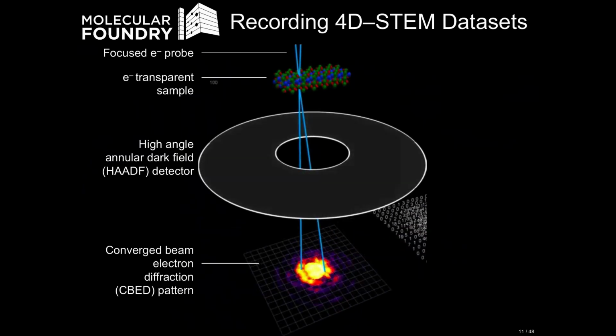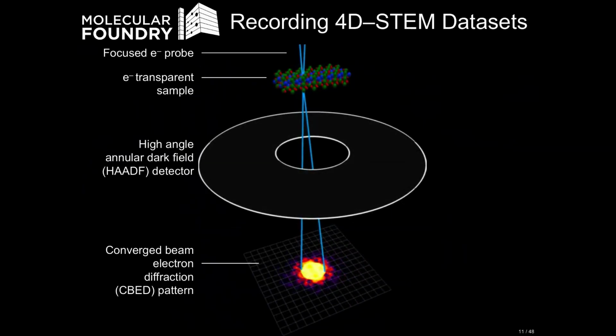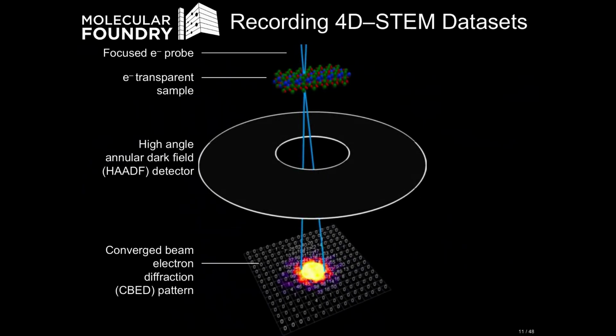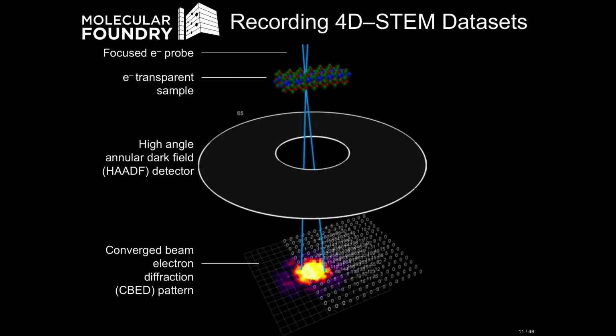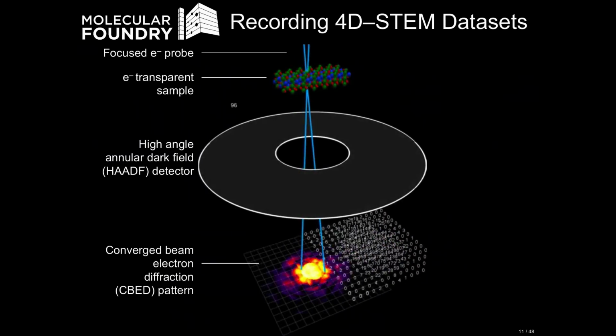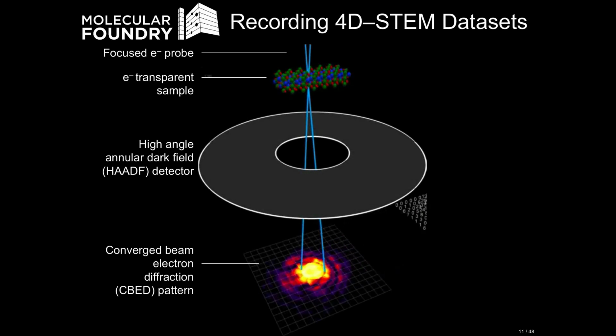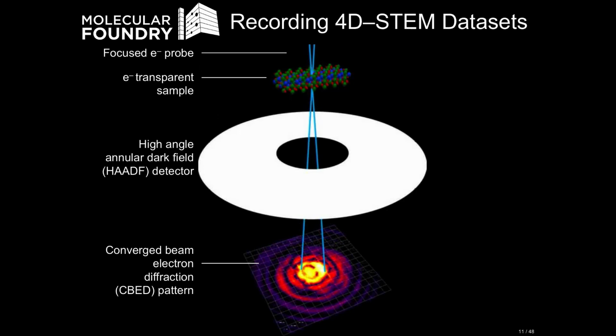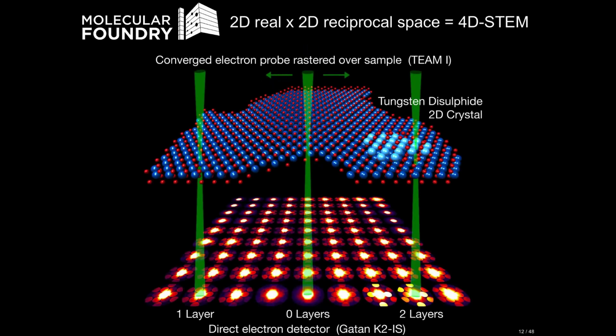So this is where the name 4D STEM comes from, because we typically scan the beam in a two-dimensional pattern on the sample surface, a grid of probe positions, and we also record a full two-dimensional image at each probe position. And so this creates a four-dimensional data set that we're going to use to do the experiments that I'm going to show today here.